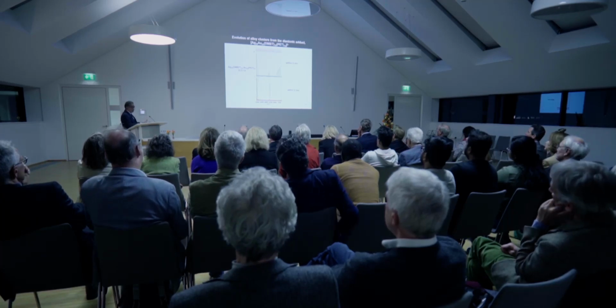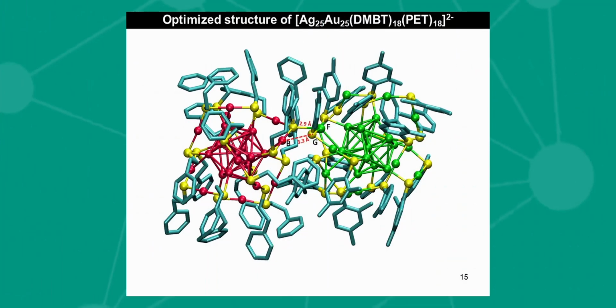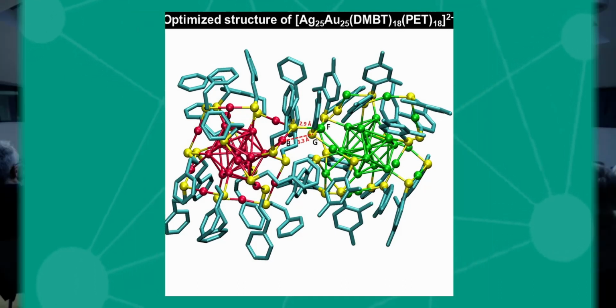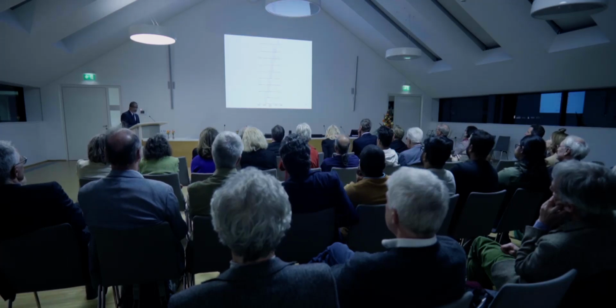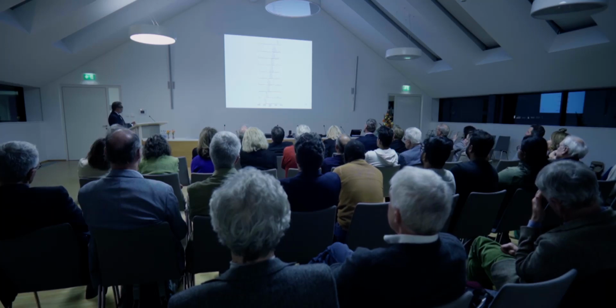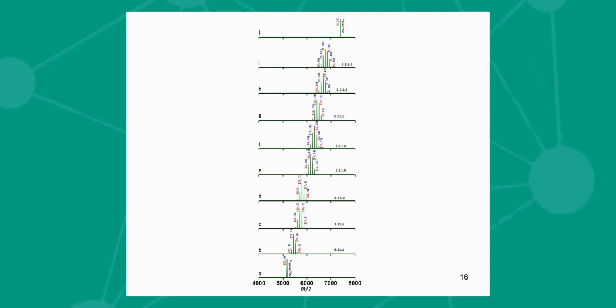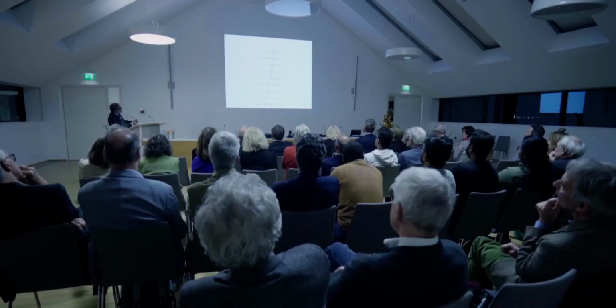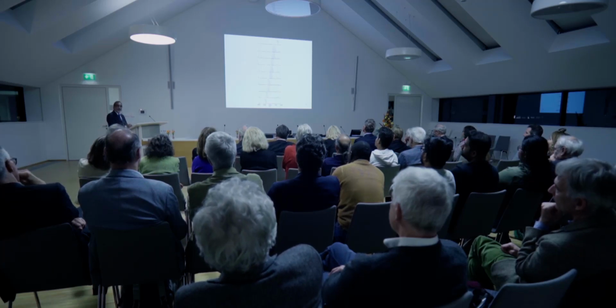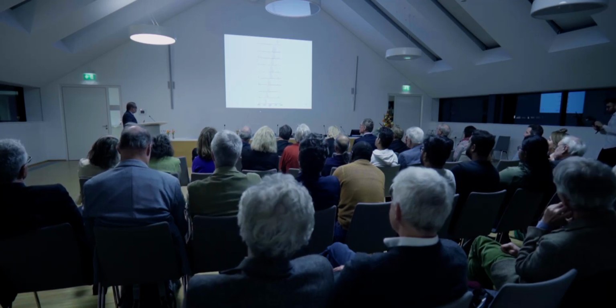And these clusters from that become many other reaction products in the course of time. Well, you can compute it. And you say that these clusters come together at interatomic distances, or intercluster distances, of things like 2.9 angstrom or 3 angstrom, where atom exchange is feasible. So to begin with, I start with silver 25 and add a little bit of gold 25, I get atom exchange. A little more gold 25 here, some more atom exchange to this equilibrium mixture. I exchange all the atoms, and I can go all the way to gold 25 by changing one atom at a time. This is not to say that silver is becoming gold. This is not alchemy, or things of that kind. This is reaction chemistry. Many other species get formed, but this is something that happens.